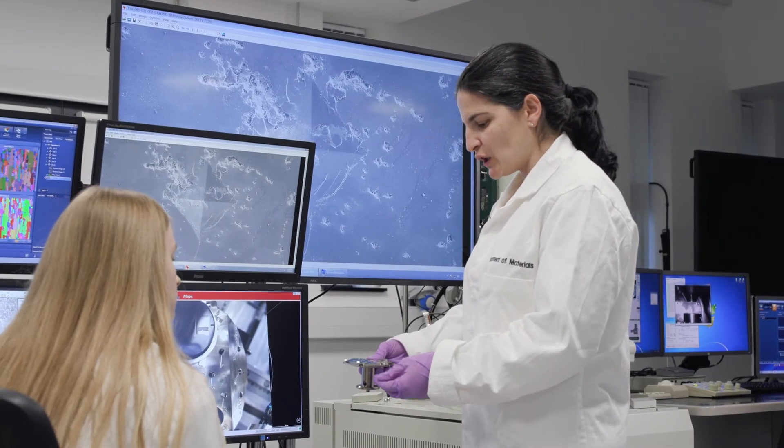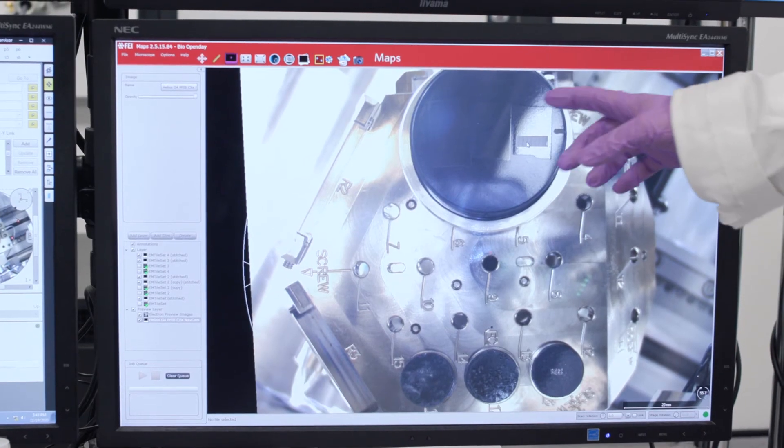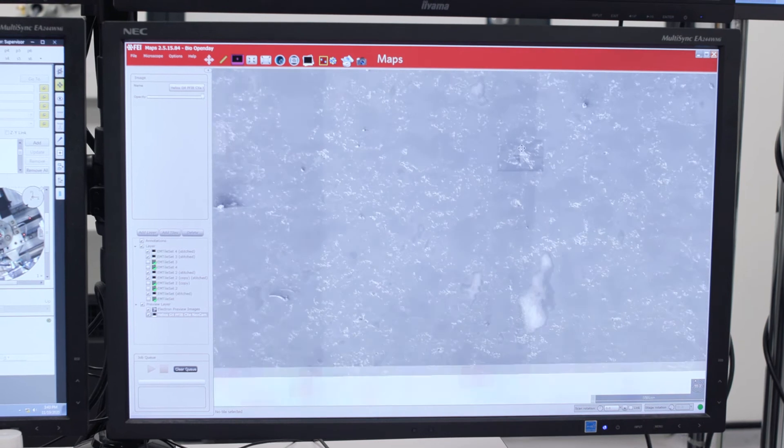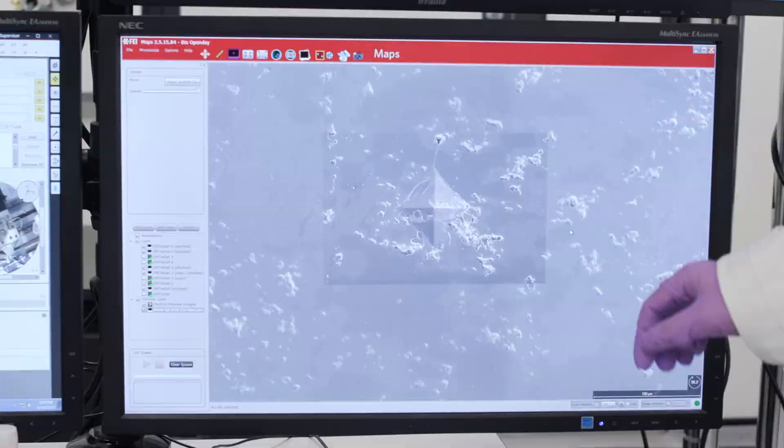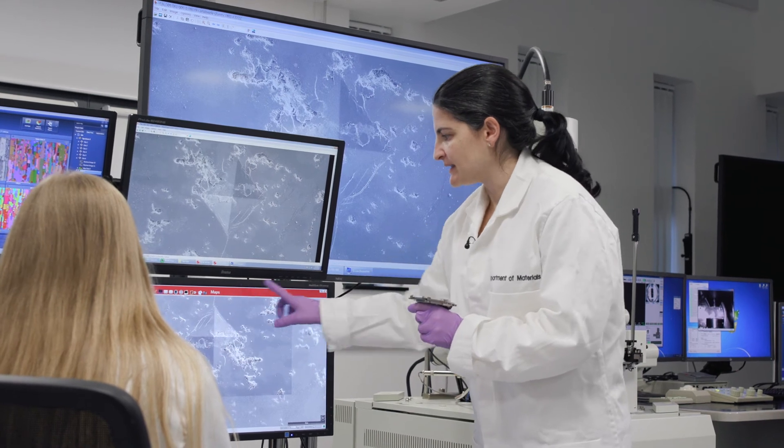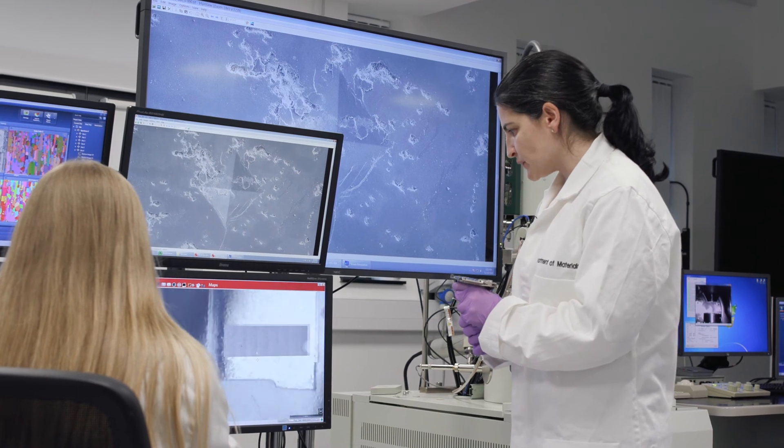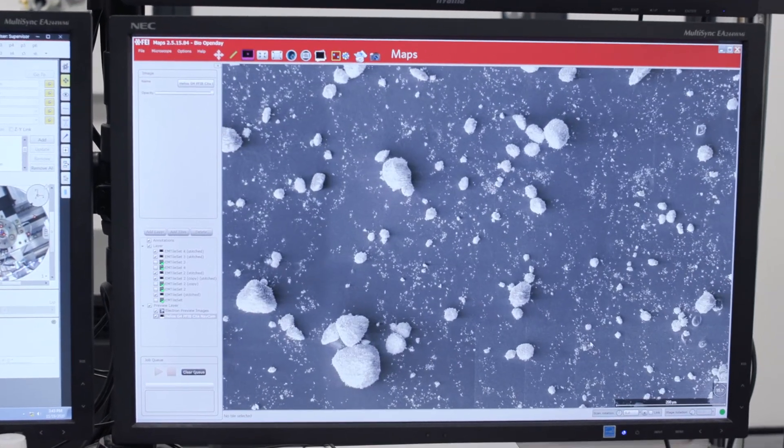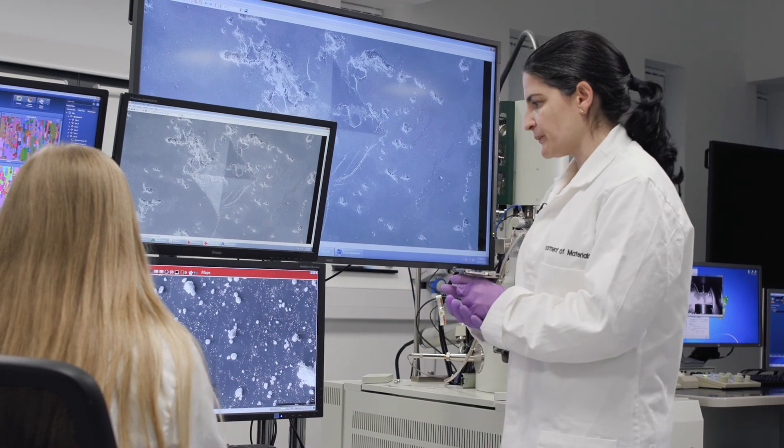So here I have some samples of materials we can analyze with this high-resolution microscope. If we look at this sample here, you can zoom in and we can find the indentation area. This is the indentation area that we analyze with the hardness test. You can see the mark of the tip, but you can also see fragments of the material that has been removed from the sample. Those are the fragments. They have different shapes and sizes, as you can see in the picture.